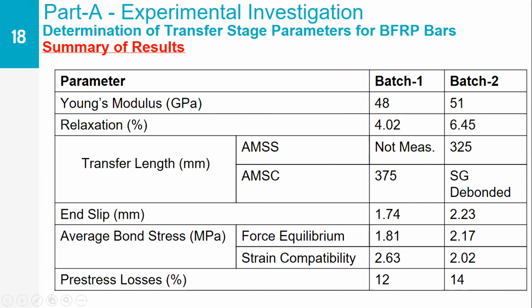And for the second batch of specimens, the strain gauges that were mounted on the concrete unfortunately debonded, so we could not get the strain profile from the concrete surface. However, from the strain gauges which were mounted on the BFRP bars embedded inside the concrete, we got the strain profile, and the transfer length obtained from that batch of specimens was 325 millimeters. The end slips were also very nominal. It was between 1 to 2 millimeters. So this basically gives you an idea that the transfer length of BFRP bars is approximately of the order of 40 times the diameter of the bars, and the pre-stress losses here were between 12 and 14%.